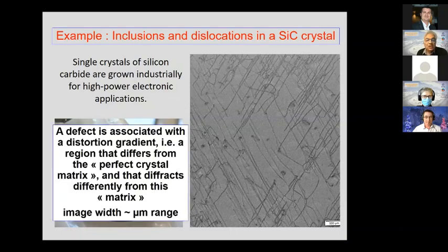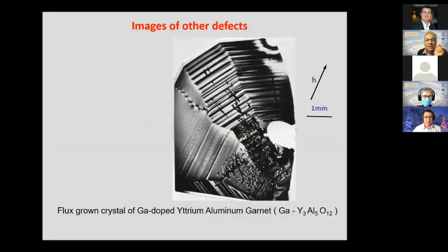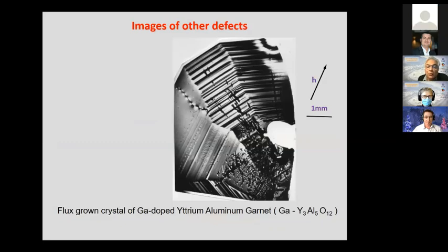Why do you see that? You see that because a defect is associated with a distortion gradient, that is a region that differs from the perfect crystal matrix, and that diffracts differently from this matrix. So you see this region around the defect which is distorted. And so that means the image widths correspond to this region and is in the micrometer range, even if the defect is very small.